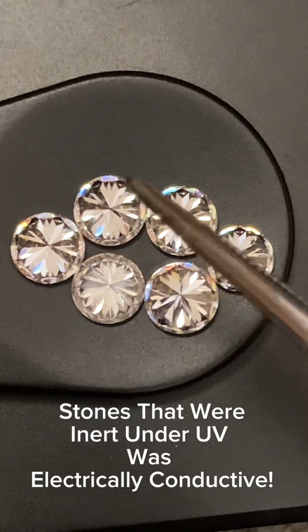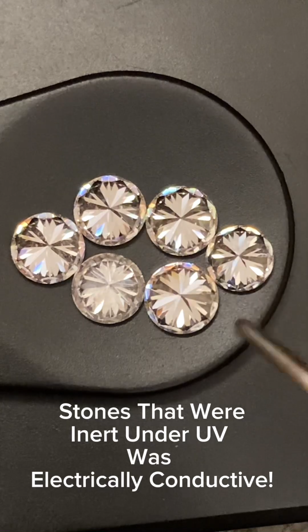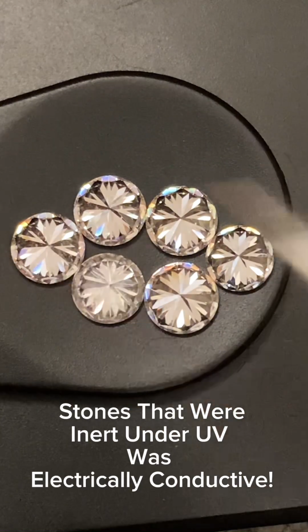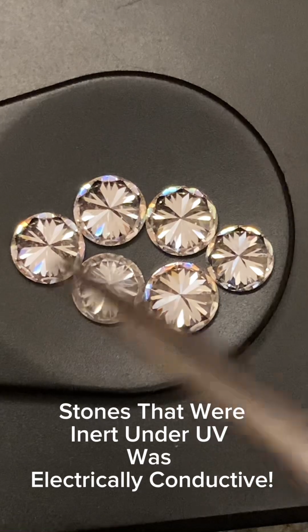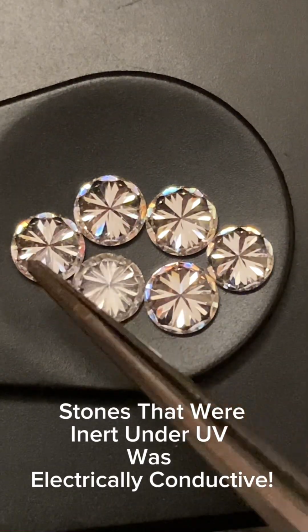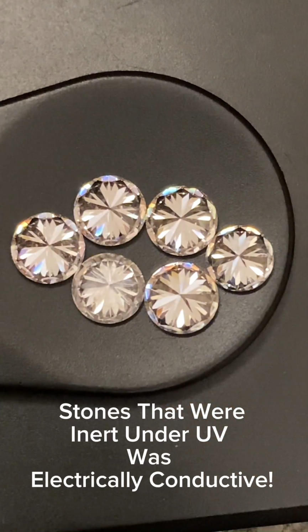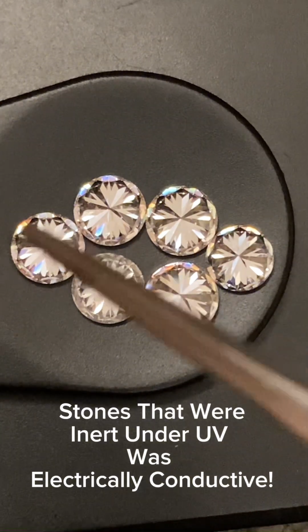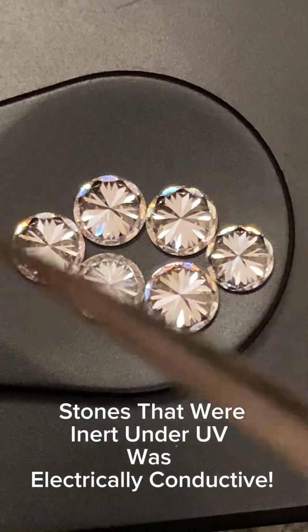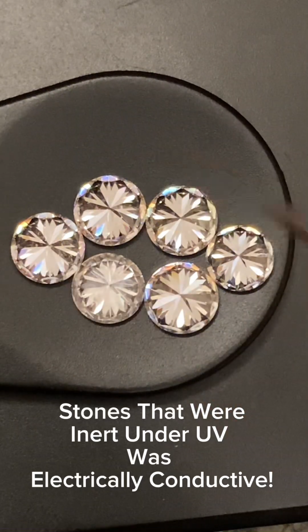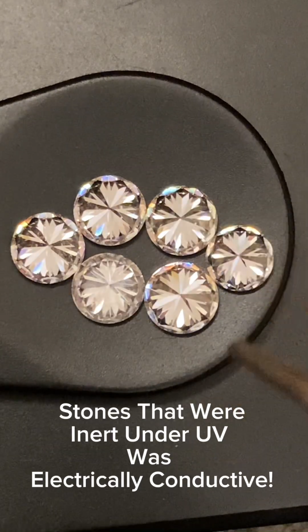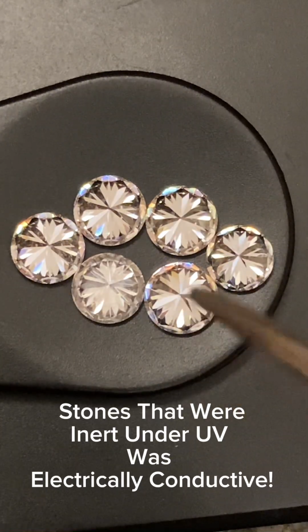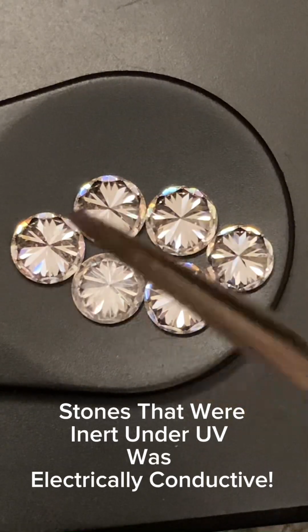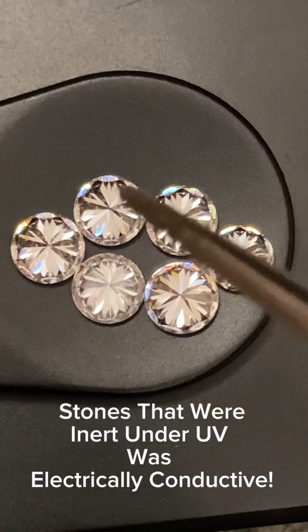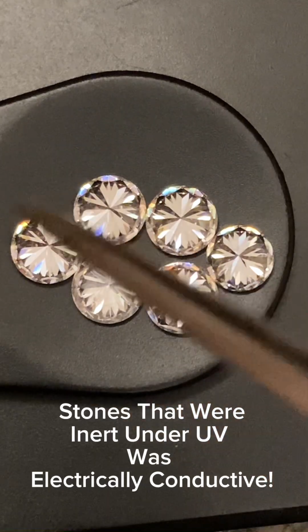This stone and this stone had no fluorescence or phosphorescence, and this stone also did not have any phosphorescence or fluorescence. So in the results, when we used the electrical conductometer, we had three stones, 1, 2, 3, that were electrical conductors. These three stones right here did not have any phosphorescence or fluorescence. They remained inert under both wavelengths. So there's three, so that's how many we had.